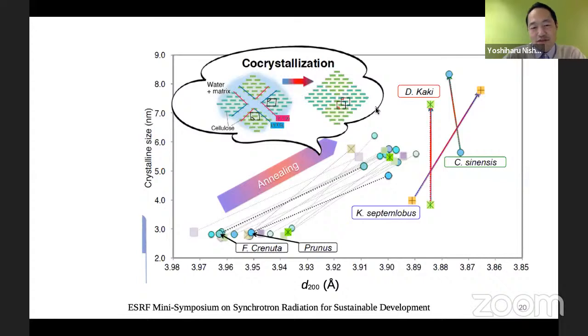So this co-crystallization behavior in the lateral range, probably this kind of thing is also happening during the recycling process that leads to the concentration of disordered region along the crystalline in the longer axis.